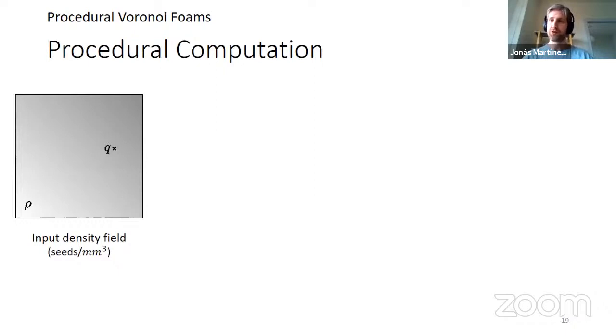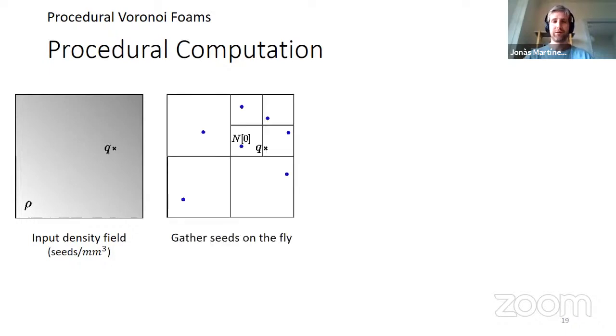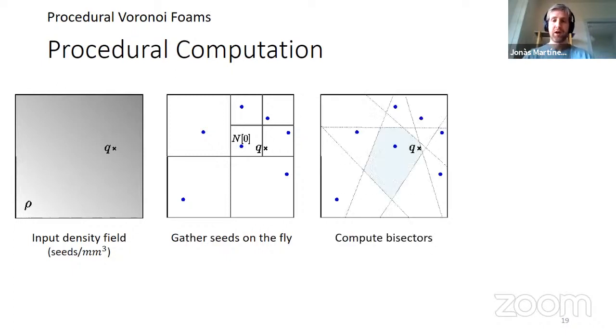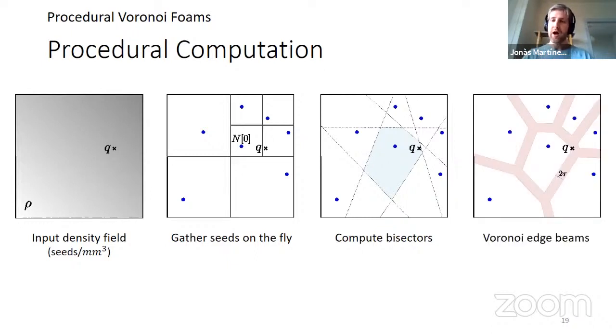So how do we compute this in a procedural fashion? Basically, we have some input density field given by the user that indicates some density distribution of the seeds. And then you have some point Q, and you want to determine whether it's solid or void. So what we do is recursive gathering of seeds of the Voronoi diagram around this point. And we compute some local bisectors on the point Q. And then we can determine if the point belongs to a Voronoi edge or not. So we do that without ever explicitly storing the seeds or any mesh. It comes in a procedural form.